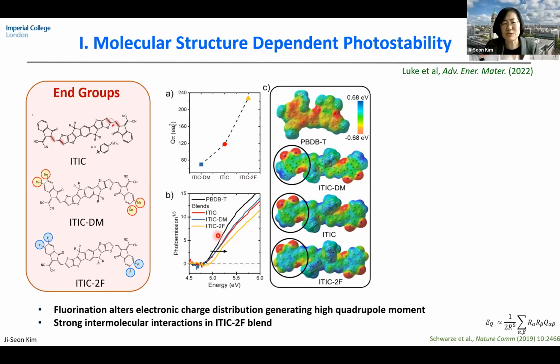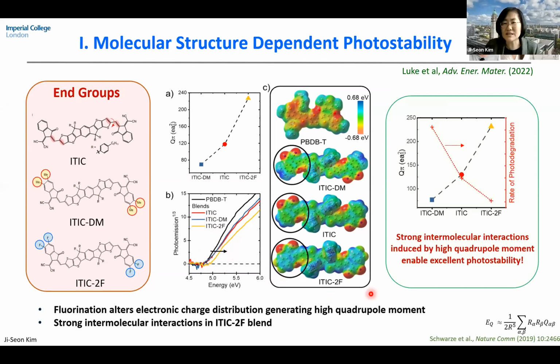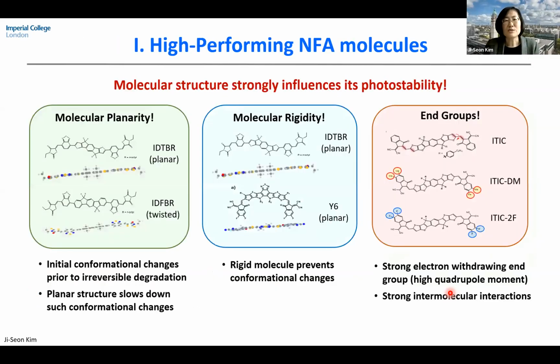In the ITIC-2F case, it changes the donor polymer HOMO energy, caused by this strong intermolecular interaction. Therefore, we proposed that this strong intermolecular interaction, induced by the high quadrupole moment of the NFA, enables the excellent photostability of NFA as well as blend systems. So in the first part, I briefly explained how important the molecular structure, particularly of NFAs, is in order to study photostability.